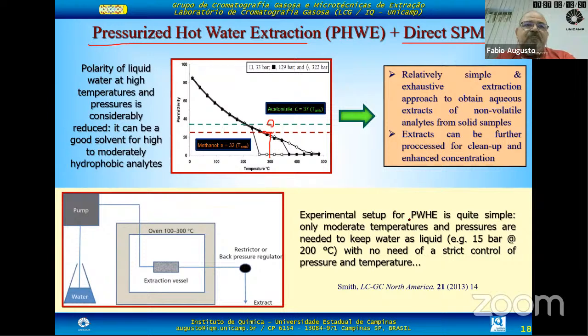The experimental setup for pressurized hot water extraction is very simple. Pressurized solvent extraction is a modality of extraction that can be very cumbersome if you use organic solvents, but for water it's simple, because you just need a moderate pressure to keep water liquid at very high temperature. 15 bars is enough to keep the water liquid at 200 degrees Celsius. You do not need very strict control of pressure and temperature. You need a pump to pump the water to an extracting cell. The extracting cell has to be kept in an oven, of course. At the exit of the system, you need a back pressure regulator, some device that keeps the pressure in the system behind it. Control it, pass the water at high temperature through your sample, and then collect the extract.